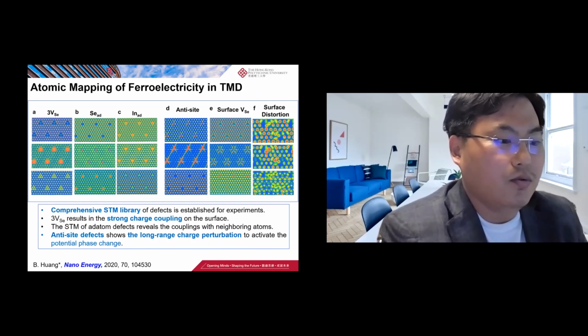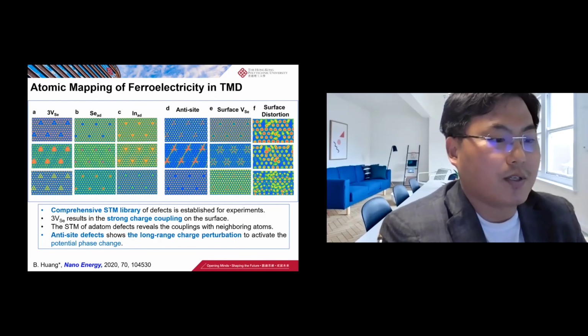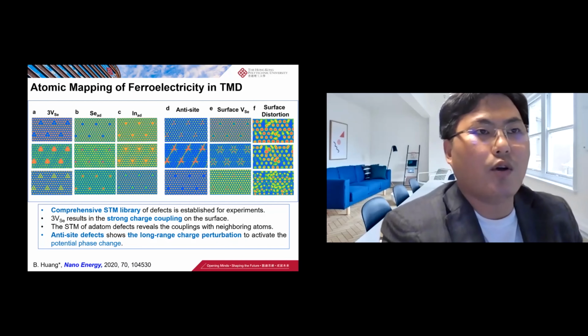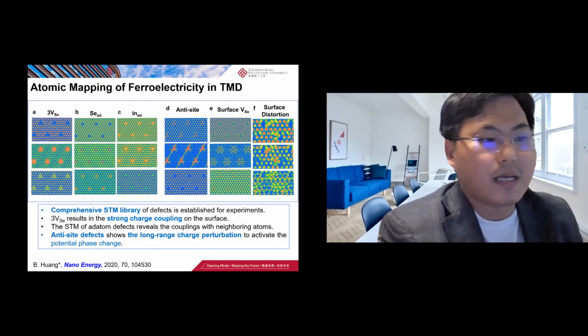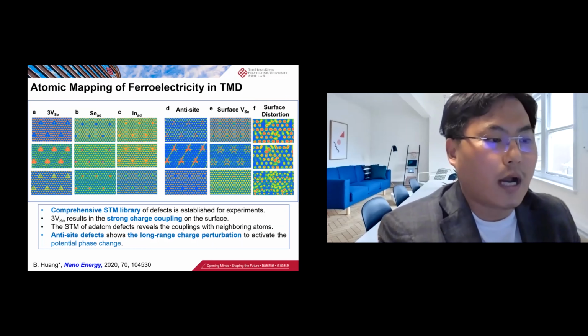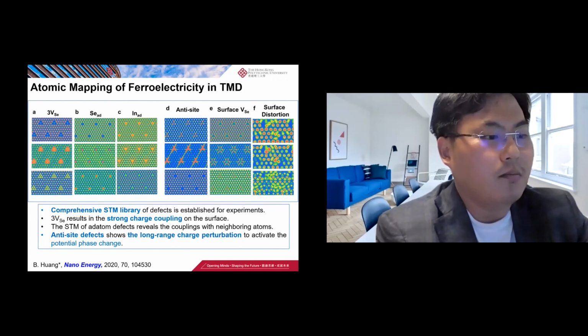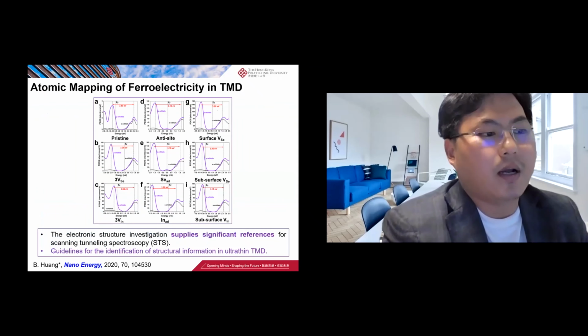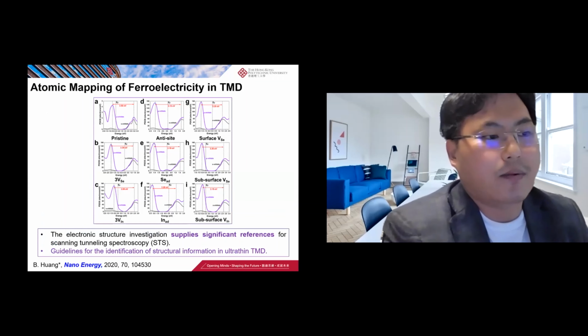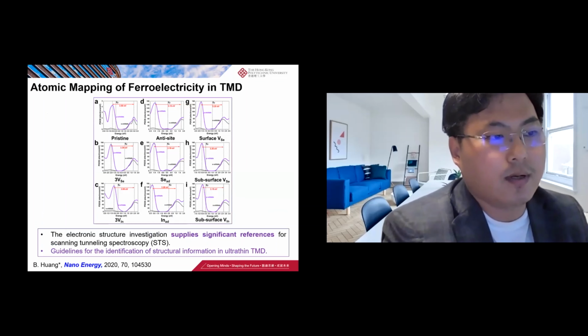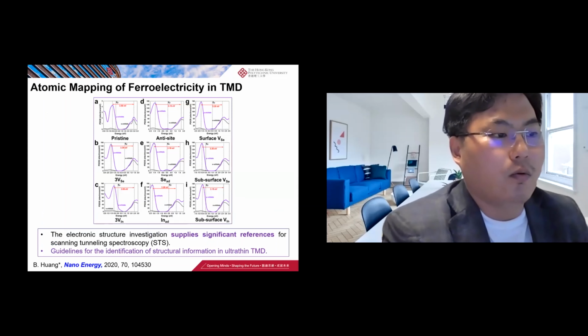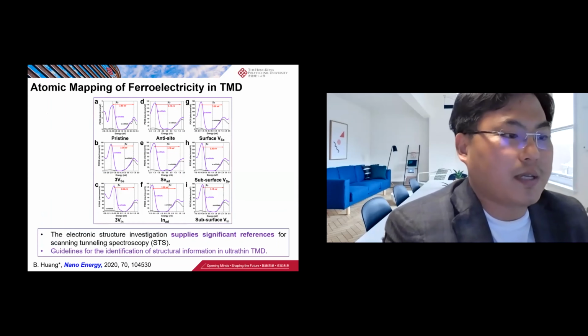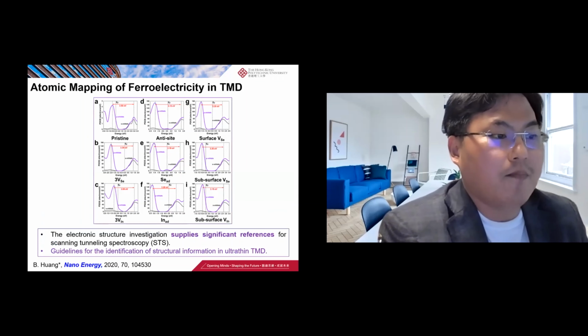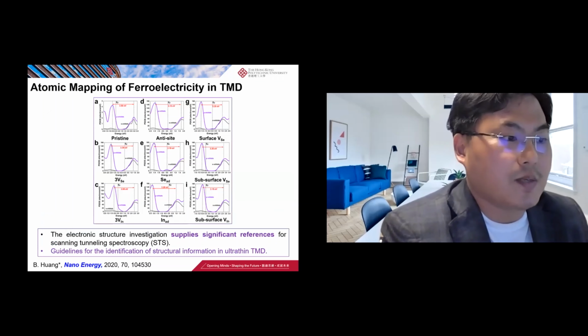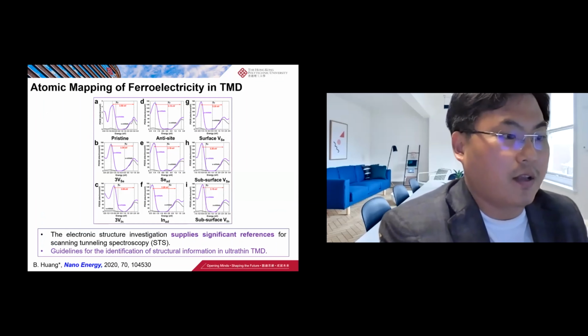It will become a highly useful tool to supply significant information and references for understanding the microstructures of different materials. So this inspires us to build this kind of library in the big data space for intrinsic defects, considering all kinds of possible combinations of intrinsic defects during synthesis within the range of two-dimensional materials. We also consider the limitations of the experimental range from 4 Kelvin to room temperature, covering liquid helium to liquid nitrogen temperatures. We are fully capable of simulating the wide temperature range of the STS. Besides the simulated STM images, we can simulate the scanning tunneling spectroscopy based on our surface PDOS, also offering significant information for comparison.